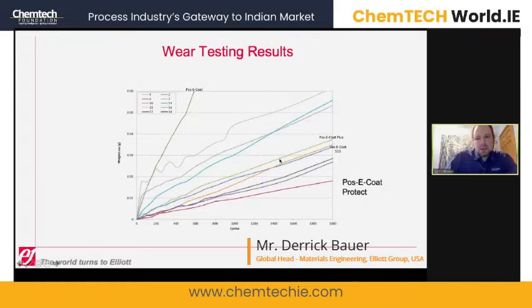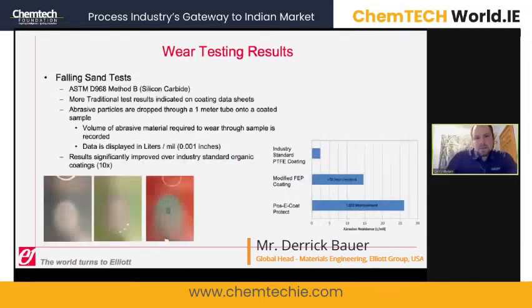As seen here on this graph, the Pos-E-Coat Protect far outperformed the others. It has better wear resistance than the industry standard coatings that are currently applied. While this is not a true fit for service test, this does show that it has higher durability than the coatings that are commonly used in the industry.